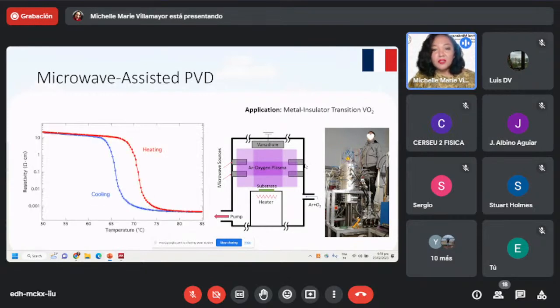Now, vanadium dioxide is an interesting material because it's a metal-insulator transition material. It means that at certain temperature, it acts as a metal, and at other temperatures, it acts as an insulator. So for vanadium dioxide, for temperatures less than 68 degrees, it's an insulator. So you can see here, this is the resistivity, which is in ohm centimeter. At lower than 68 degrees Celsius, it has a very high resistivity. However, if you subject this material to higher temperature, it transitions to being a metallic material. However, if you take away the heat and cool it down, the resistivity goes up again.